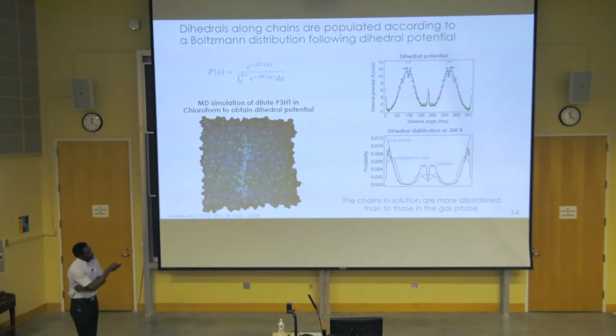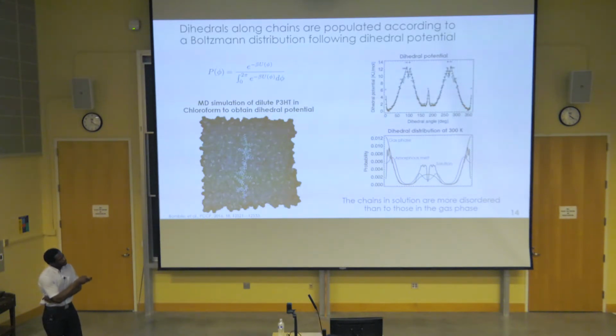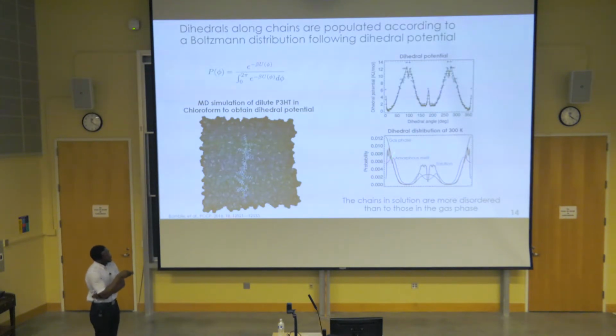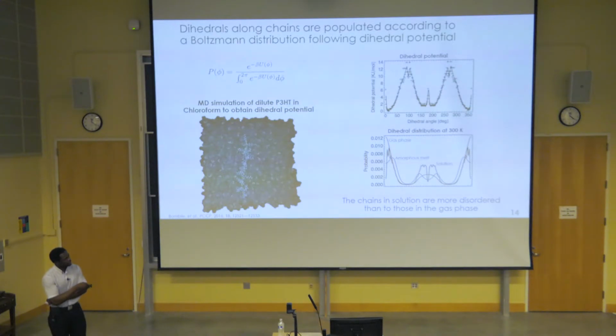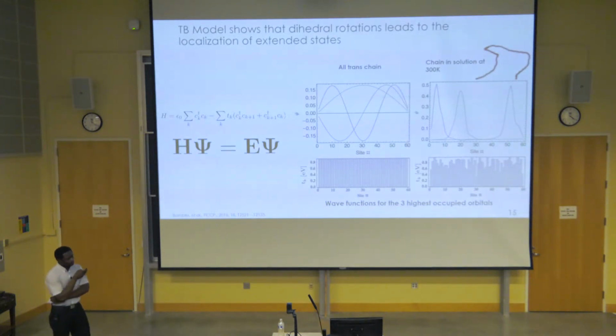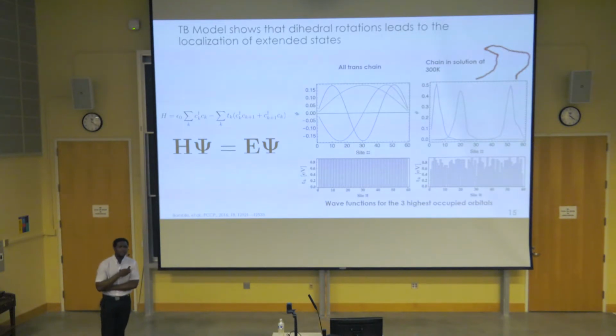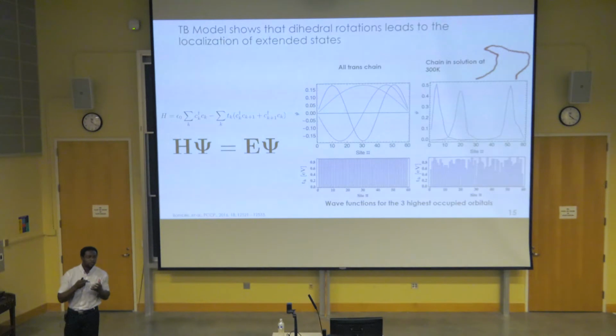And one thing to note is we have a different dihedral distribution depending on the medium in which the chain is found. The chain in solution appears to be more disordered than the chain in the amorphous melt or the chain in the gas phase, as evidenced by the less uniform dihedral distribution for the chains in solution. So having the two ingredients that we need, we then used our tight binding Hamiltonian modulated by dihedral rotations to look at how the highest occupied electronic states, as relevant for the conduction of holes, are in a chain in two different situations.